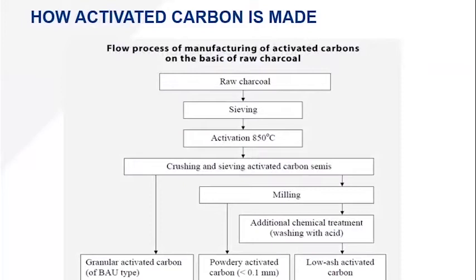So how is activated carbon made? You take that raw charcoal — made by burning wood material or coal in a low-oxygen environment, then breaking that into chunks. It's put into a high-temperature furnace with no oxygen, and that's critical because we don't want combustion; we want thermal degradation, which is completely different. That's done at 850°C. If oxygen were present, it would combust the charcoal into nothing but ash. Once it comes out of that process, it is crushed and sieved to the desired size.